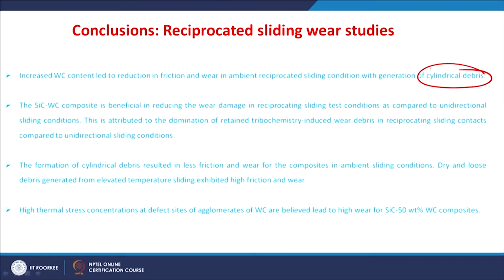So, cylindrical debris formation is observed only in the ambient conditions. The silicon carbide tungsten carbide composite is beneficial in reducing the wear damage in reciprocated sliding test conditions as compared to the unidirectional sliding test conditions. This particular observation is attributed to the domination of retained tribochemistry induced wear debris. Because of the longer time for the debris in a contact, the tribochemistry induced wear is much retained. So, in the reciprocated sliding conditions, it is much beneficial.